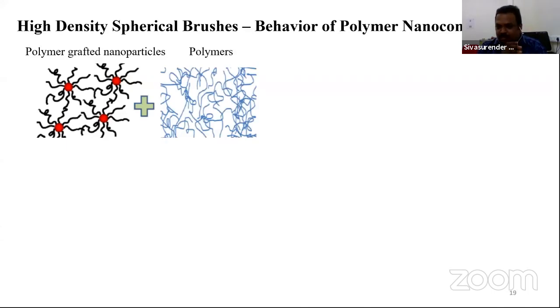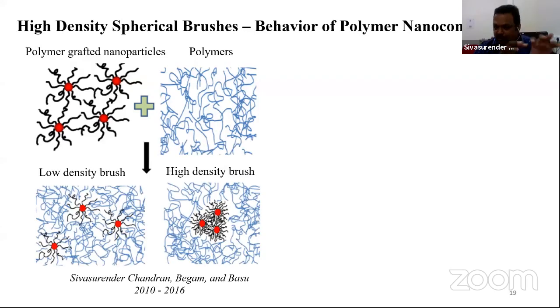With a simple polymer melt. Now, from our understanding of what we have just seen with the flat brush surfaces, we know that when the density of this brush is very low, it doesn't matter. They just interpenetrate, because this is polystyrene; both the grafting and the matrix are polystyrene. But the moment you increase the density of the brushes covering the nanoparticle, they cannot interpenetrate with the matrix, right? So the particles tend to aggregate, and on top of that, right at the interface between the grafting chains and the matrix chains, there exists a depleted region, a region where you have lower density of the polymers, right?